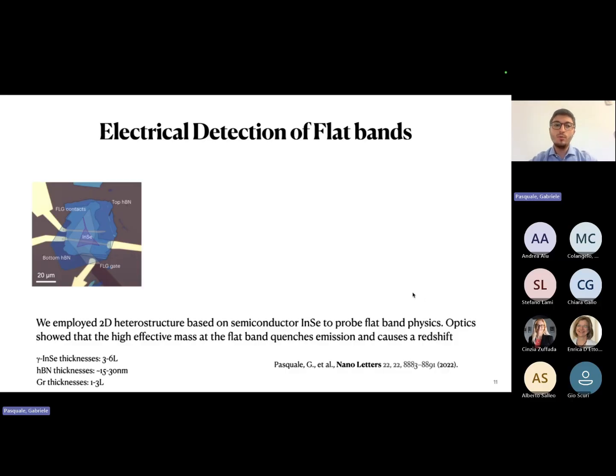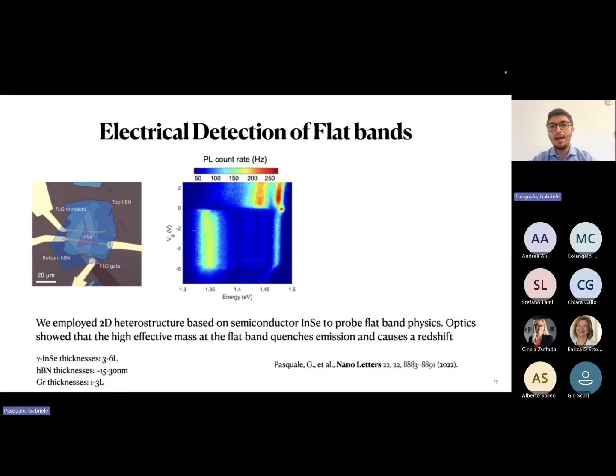The work I'm going to talk about now is the first electrical detection of flat bands, which is something that we did in two-dimensional heterostructures based on a flat band semiconductor, indium selenide. We saw some hints of flat band physics from photoluminescence, where we observed that at the valence band edge of this material, where the flat band is located, we see a strong quenching of the photoluminescence and a strong redshift, which is linked to the high effective mass of carriers at the flat band.